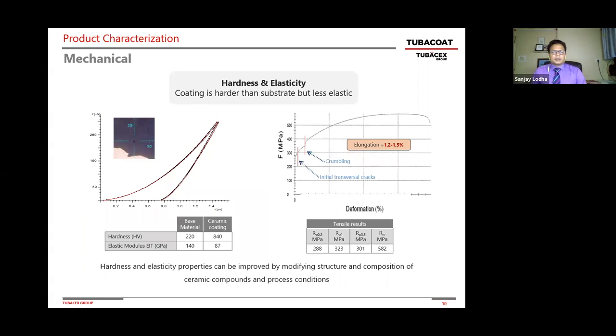This slide is another interesting slide that shows on the left side the load displacement curve. When you put a certain amount of load, how is the surface reacting? And when I look at the hardness of the coated tube, that is 840 Vickers number compared to 220 for the base material. So I'm able to bring a hardness 4 times higher than the base material. But it does come at a cost to pay.